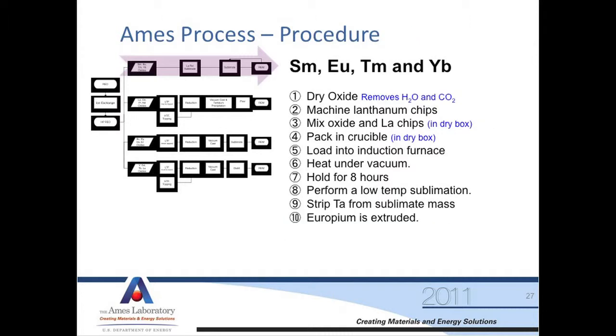Process. We have to prepare all our tantalum crucibles in advance. We have to dry the oxide to desorb any water and carbon dioxide. Then we have to make lanthanum chips for reduction, and we mix those together in a bag, kind of like making a shake and bake, and stuff those into our tantalum crucible, put it in an induction furnace, and heat it all under vacuum. That's where the reaction takes place, with lanthanum becoming lanthanum oxide, and the metal, for example samarium, being released.